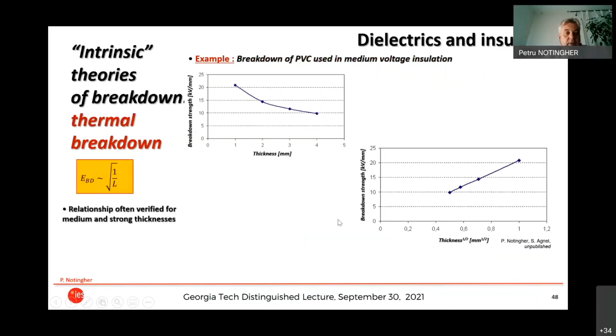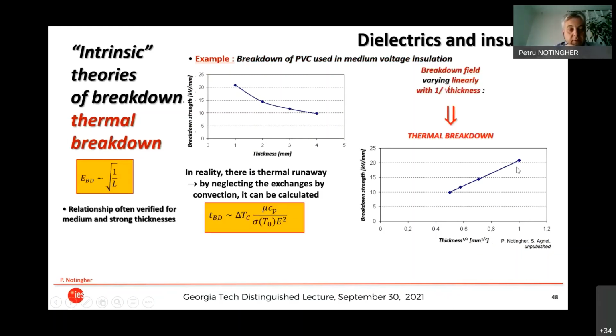And this works quite well in medium and strong thickness materials, as the example that I have here. You see that if you plot the breakdown strength over the thickness power 1 over 2, you will have a straight line. So this is the witness of a thermal breakdown.